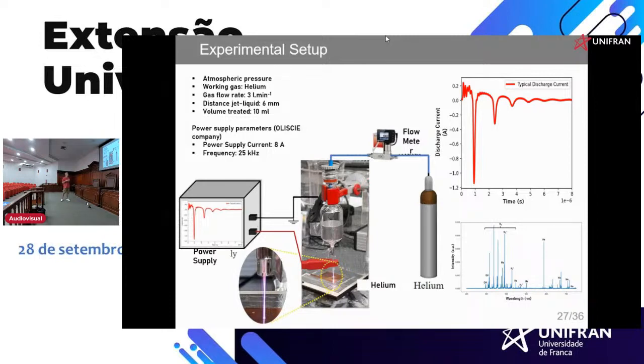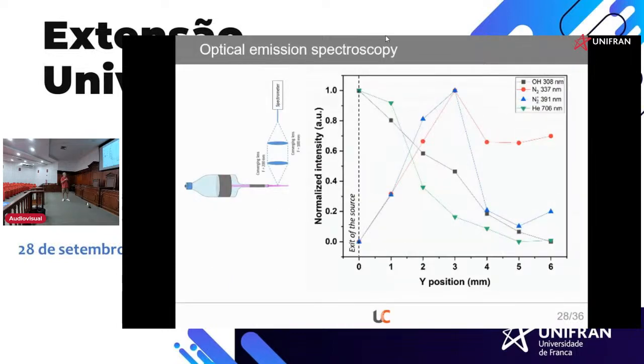So the experimental setup is quite simple. There is here a reactor, a glass reactor. We put some gas inside. Here it's helium gas. And we apply voltage between two electrodes. The plasma ignites here. And if we zoom, it goes through the surface. So we made some optical emission spectroscopy and some current measurement to characterize the plasma. We also made some optical emission spectroscopy from the nozzle to the surface.